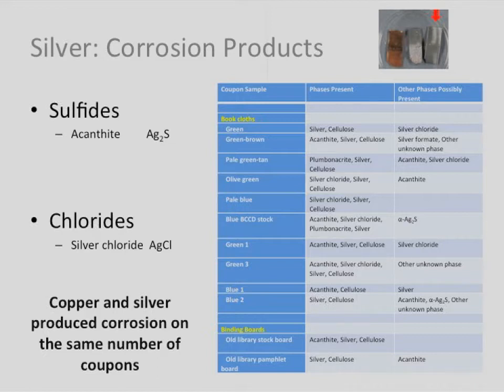And here we have 99.99 something 9% silver, so it's pretty stable. You can get chloride formation, you get sulfide formation. We so clearly see these phases here, but you don't get a ton of it.